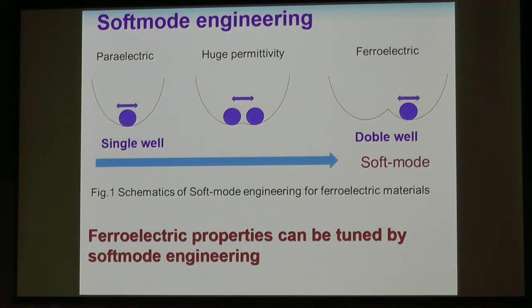This phase has a very small energy barrier between two variants. So the ion moves over a very large space here. So it shows very large permittivity and polarization fluctuation, as shown here.